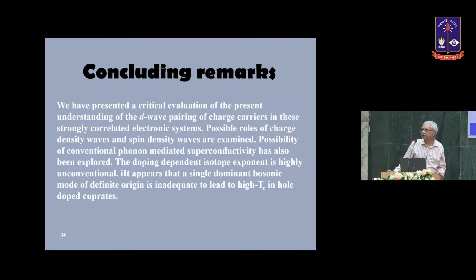So that has been our point, and we have looked at different scenarios, and our feeling is there is a mixed pairing, and the pairing has both magnetic and non-magnetic contribution. From phonon, the non-magnetic contribution is coming. The ground state, as I said, is an antiferromagnetic insulator, and as we dope, the long-range antiferromagnetic order vanishes very quickly, but there are remnants of short-range antiferromagnetic order. And that order can play a significant role to bring about pairing between the electrons.